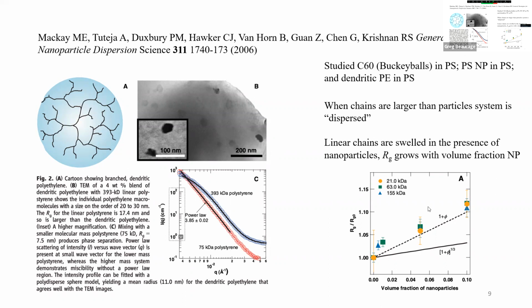So one thing he finds is that if you take the radius of gyration of the polymer, so the matrix polystyrene, you measure that with neutron scattering by deuterating like 1% of the styrene. So it's a lot of neutron scattering work. So basically, you deuterate 1% of the styrene, you have mostly hydrogenous polystyrene, and then you have the styrene beads. You can look at those 1% styrenes and see if they swell or shrink when the particles are present, right? And it turns out they swell. So they swell when the particles are present. And in a continuous way, it's linear in the composition, like how much you put in.